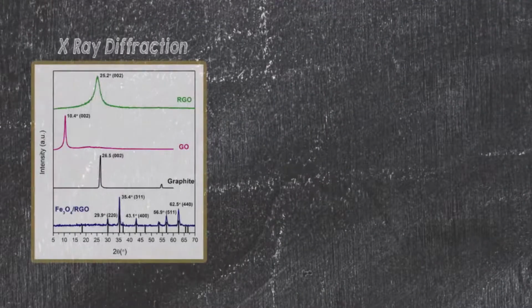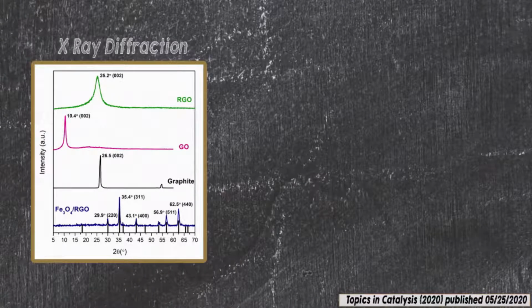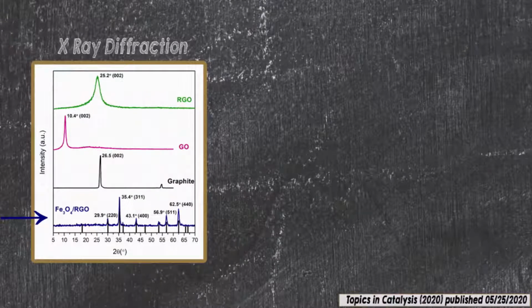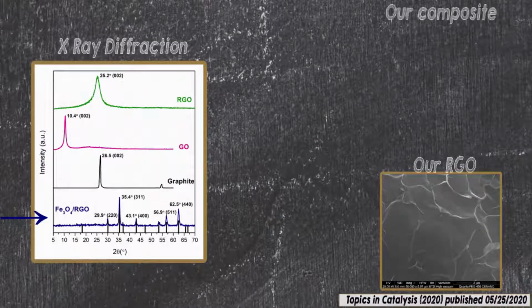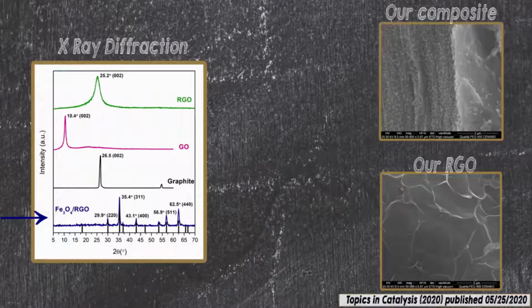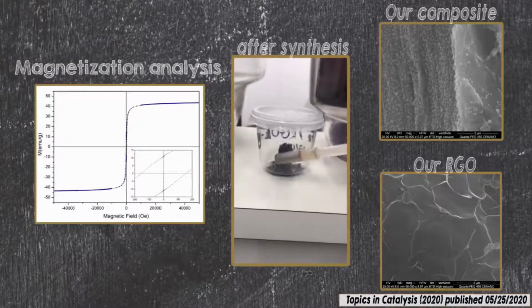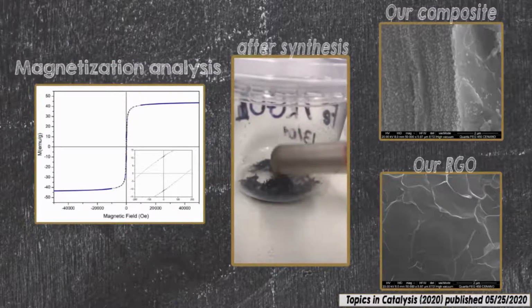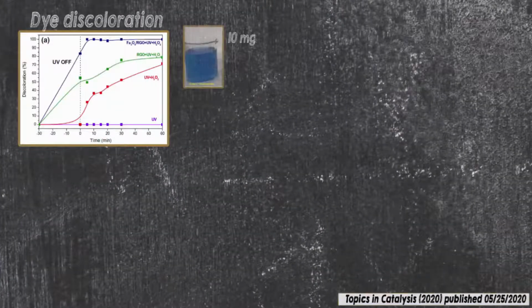X-ray diffraction patterns show that graphite, GO, and RGO are carbon materials, but they are completely different. X-ray diffraction also shows that magnetite particles were formed on RGO sheets. You can see here all these peaks related to magnetite. You can also see this in microscopic analysis. RGO shows a compacted sheet morphology, while the composite has magnetite particles on RGO sheets. Furthermore, after we synthesized the material, we approximated a magnetic bar to the composite and we observed that the composite was magnetic.